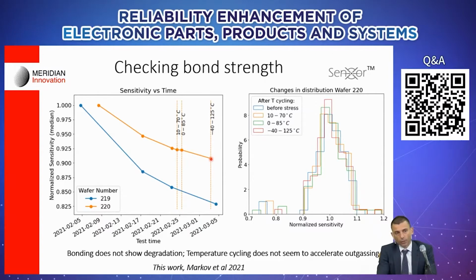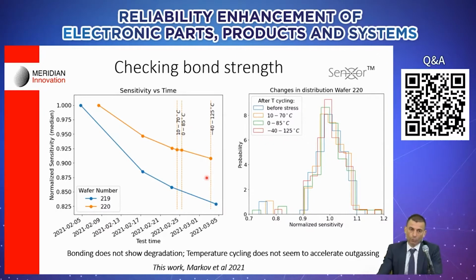So what we see in this case is that we were unable to break any bond at all, and that overall the sensitivity followed a trend that doesn't seem to be dramatically altered by the means of temperature cycling. So this tells us that, okay, for the intended operational range, which is actually 0 to 85 in this specific case, the bond strength would appear good enough, but we cannot derive from this test any predictability about how long that will be the case. So lifetime estimation is not possible from this test.